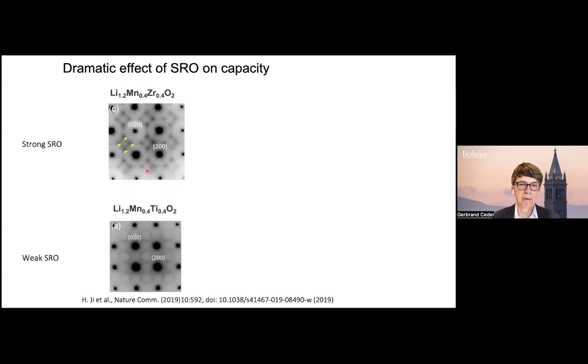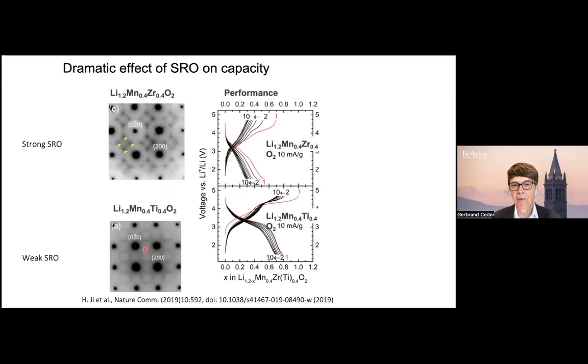You see that from the different diffuse scattering in the electron diffraction. And if you look at their performance, it's also very different. The zirconium one has very poor performance. This is the amount of lithium you can cycle, whereas the titanium one has much better performance. Again, these materials have the same particle size, same processing, but the short-range order is very different.